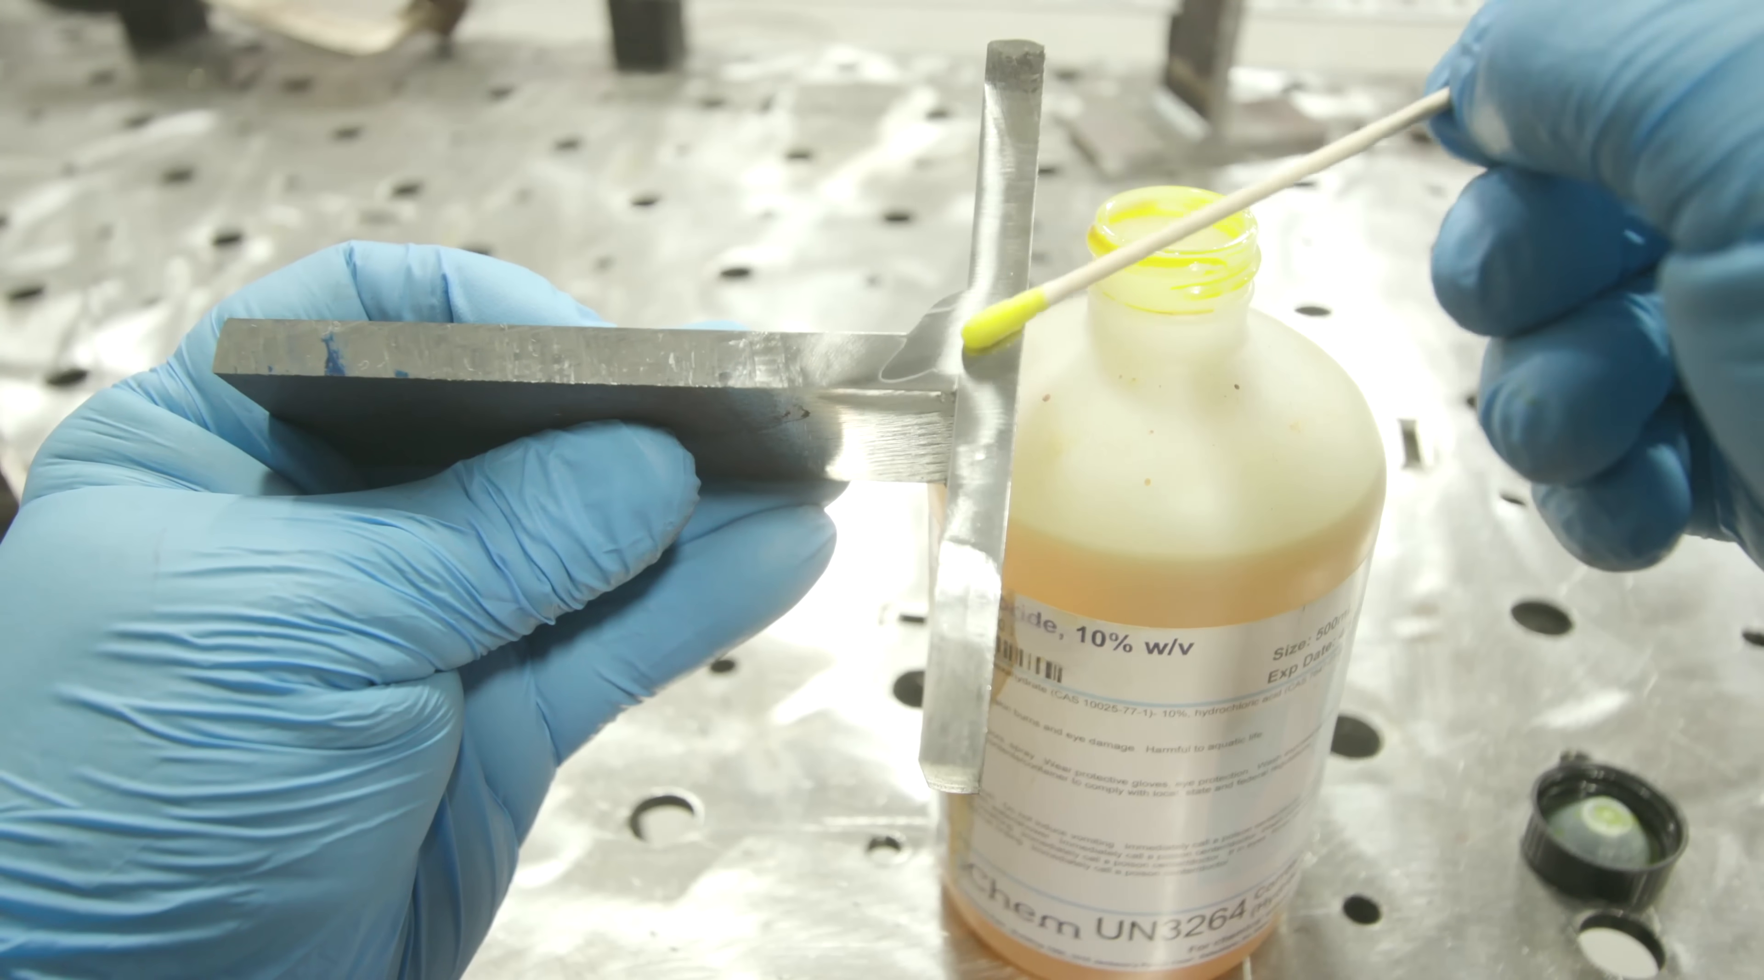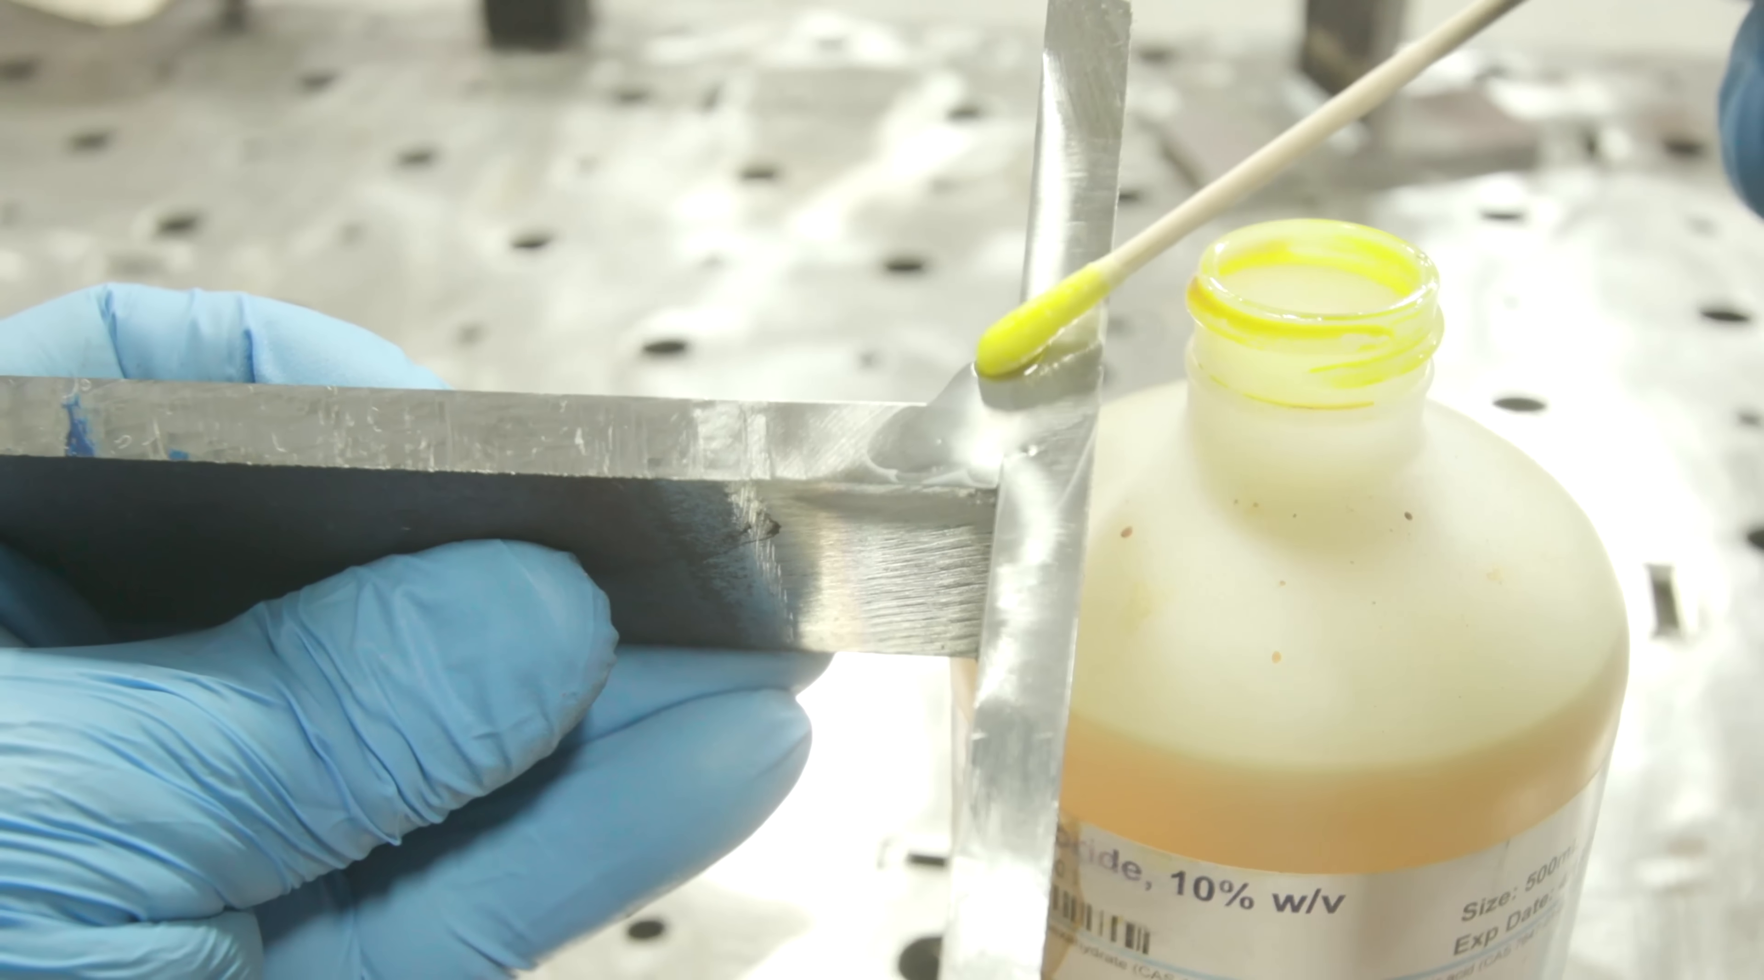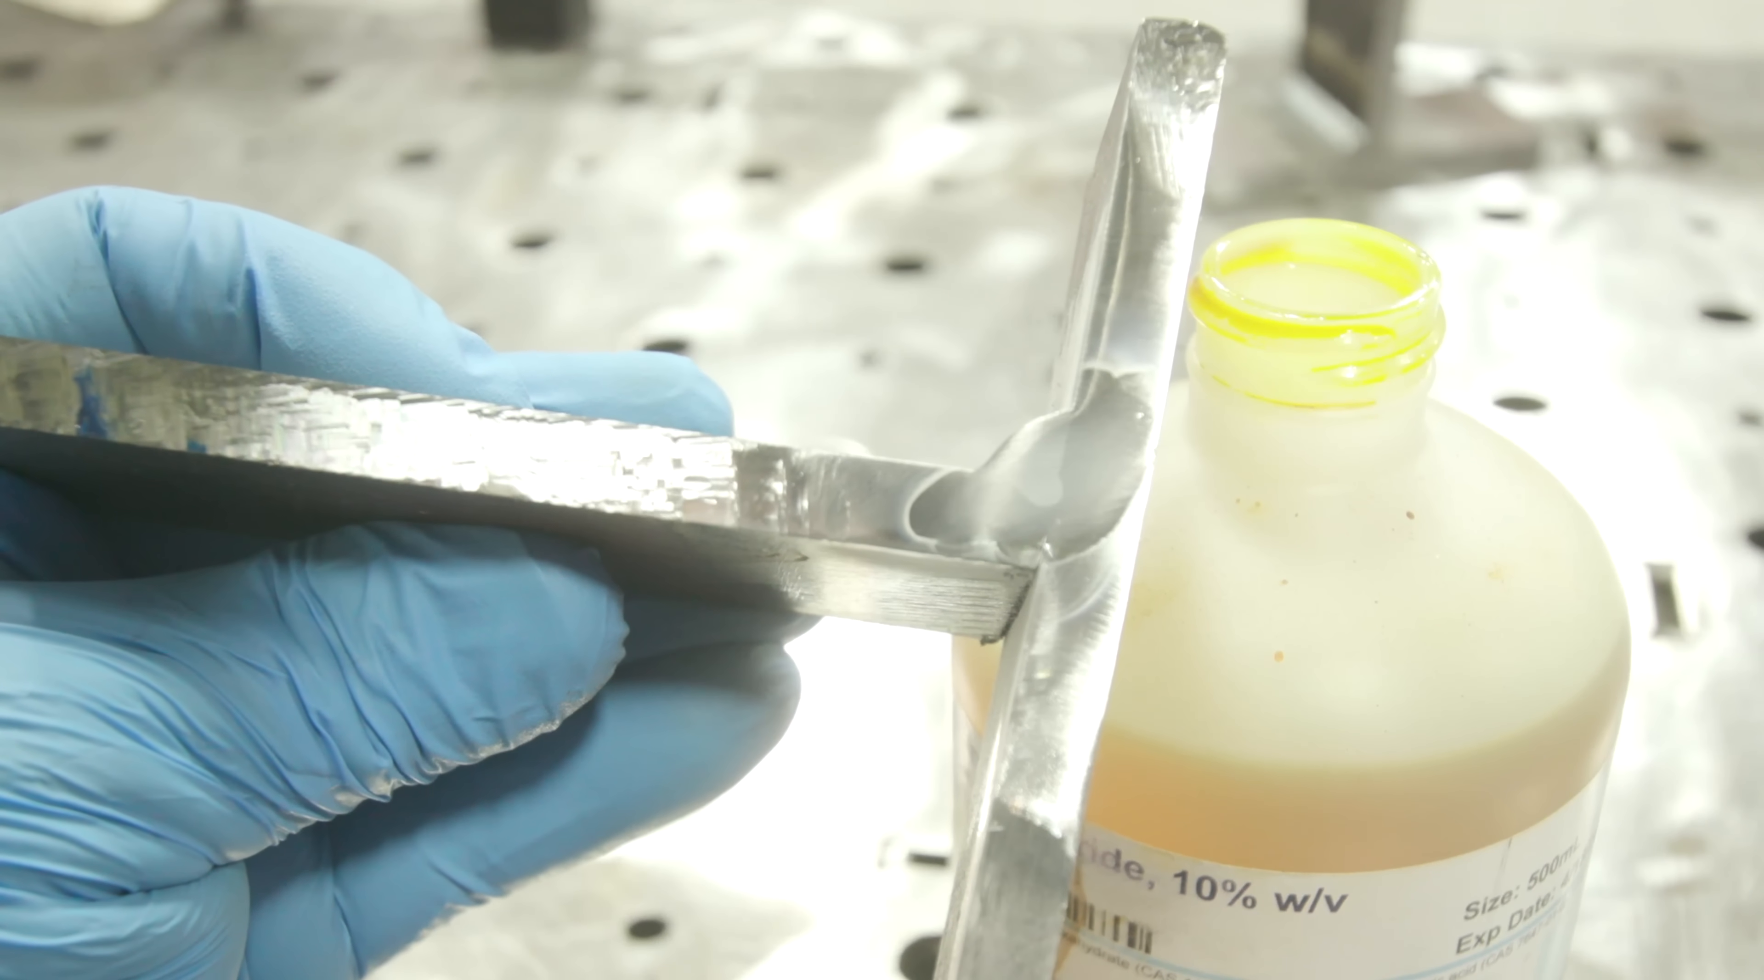And you'll see it starts to develop pretty quick. Now if you use naval jelly, you're going to have to give it maybe five, ten minutes. You can apply this stuff pretty liberally. And you can see that it's already starting to develop that weld nugget. Just let it sit right there. See, we got good penetration on this one in the horizontal and vertical leg, deep penetration of the root. It's exactly what we're after.